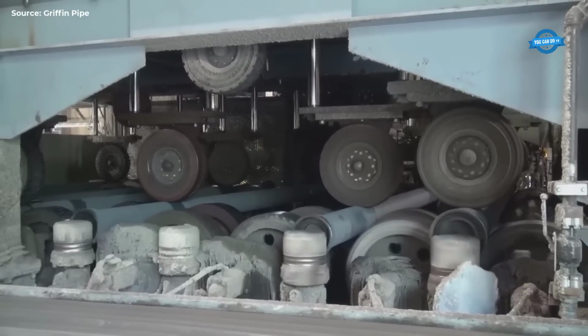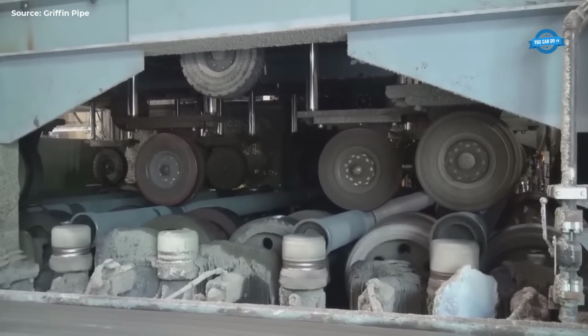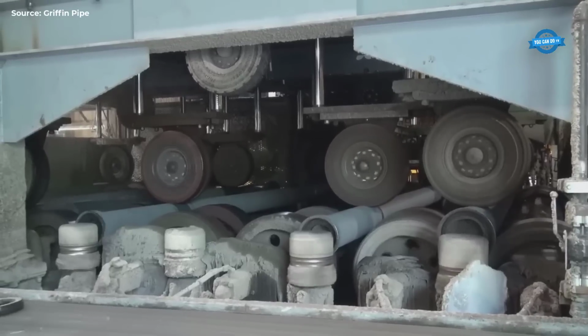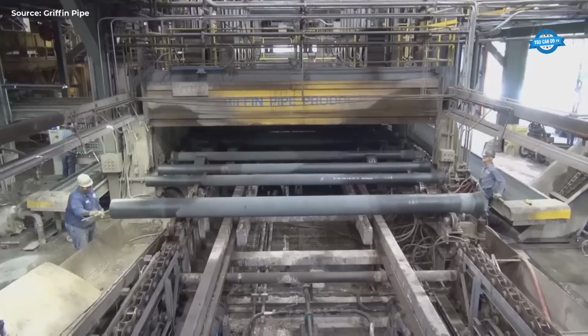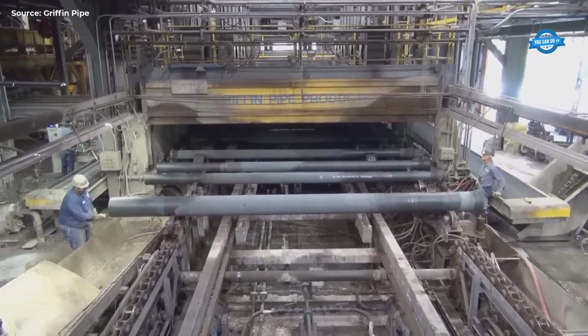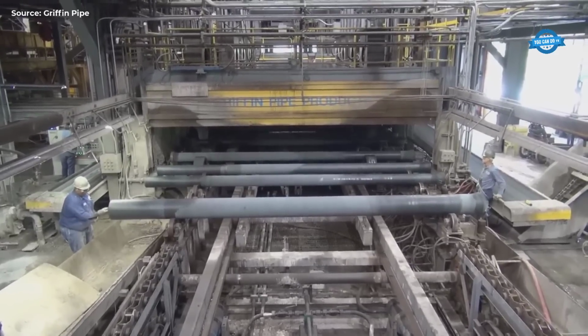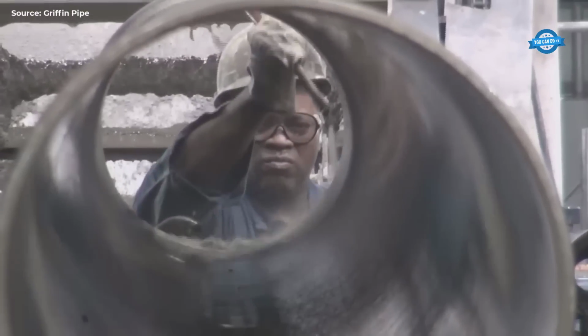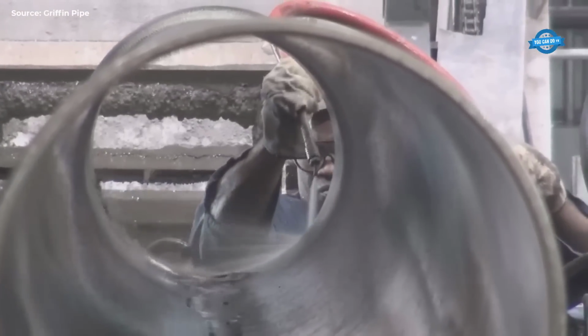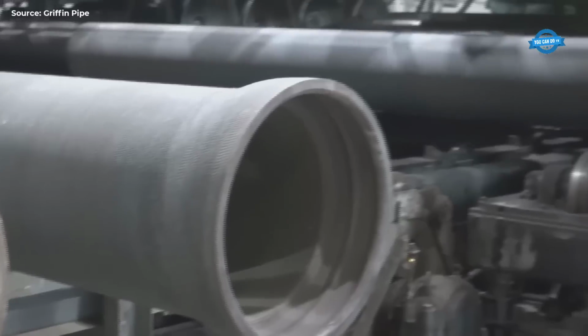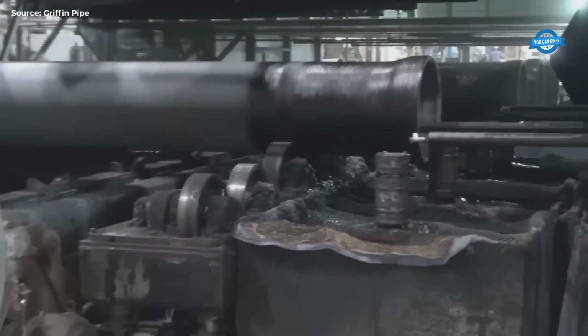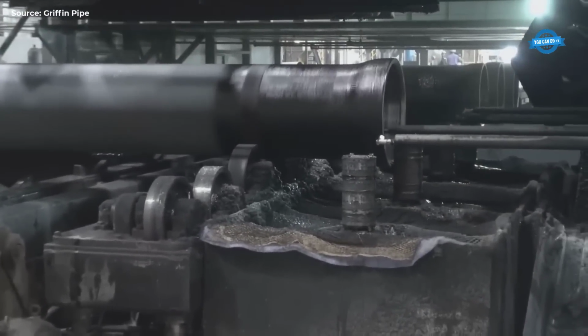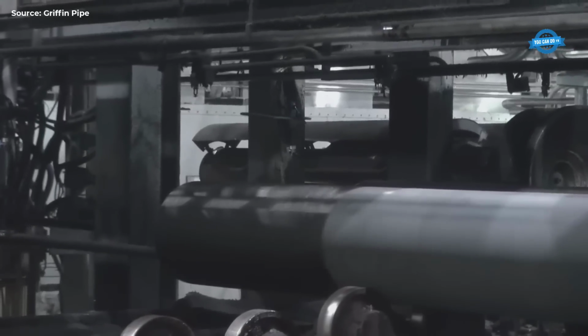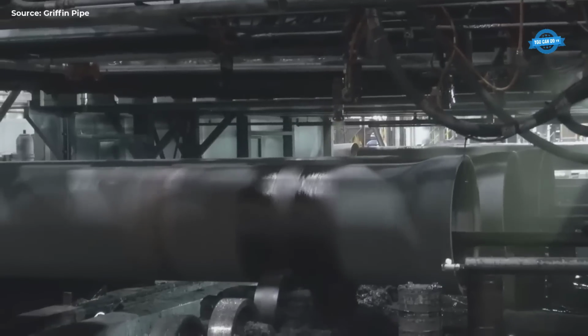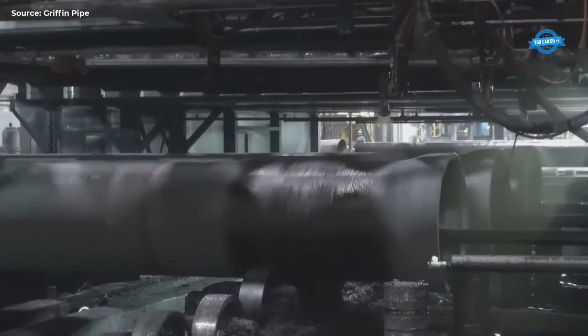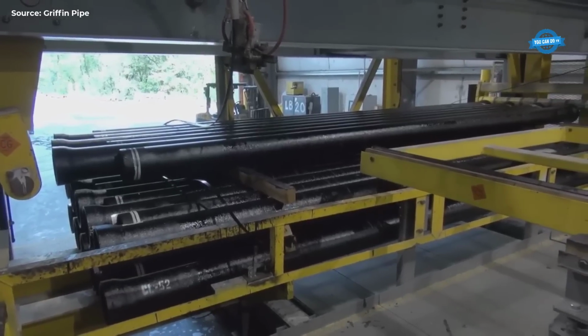Final inspection and shipping. After passing quality control, the pipe is marked with information such as the class of pipe, date of casting, and additional details. The pipe then moves to the finishing area, where it is lined with cement mortar and coated with asphalt. The cement lining process involves rotating the pipe and using centrifugal force to apply the cement to the wall of the pipe. This helps prevent the buildup of corrosive products on the pipe walls. After lining, the pipe is allowed to cure for at least 24 hours. Finally, before loading for shipment, each piece undergoes a final visual inspection to ensure the seal coat is properly set.